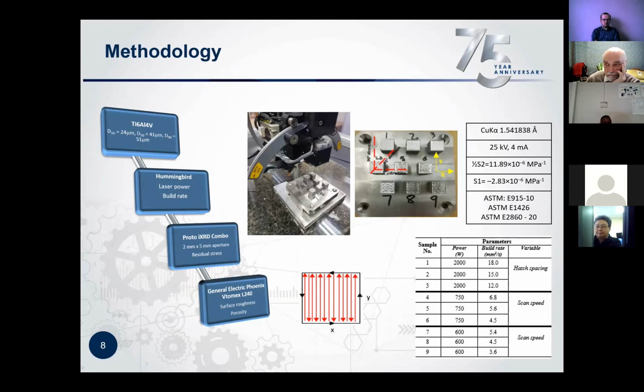Quick overview of the methodology. The powder we used is Ti64 with a particle size range of between 24 micron to about 51 micron. The system is the smaller version, which we refer to as the Hummingbird. We varied the laser power and the build rate. The build rate is influenced by three factors, which are your scanning speed, your hatch spacing, and your layer thickness. In this instance, I'm only going to be disclosing the build rate. I'm not at liberty to disclose the actual scanning speeds and hatch spacing. So instead, we are revealing the build rates and the laser power.